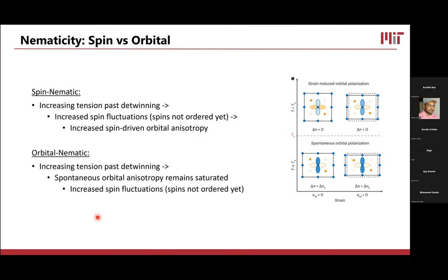Even so, I would fully expect the spin fluctuations to continue to diverge as I apply strain, because I'm making the lattice more friendly towards those spin fluctuations, and helping it get closer towards ordering. That's the basic idea. So from these pieces of data, that leads me to this idea that iron selenide has an orbital-driven nematicity.